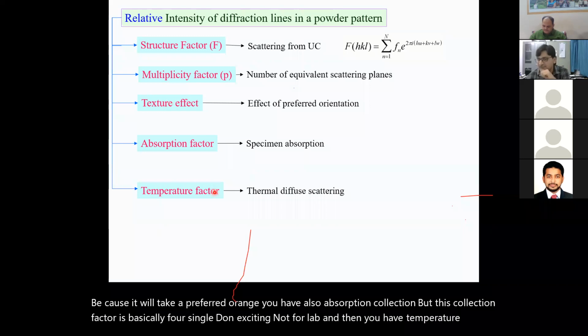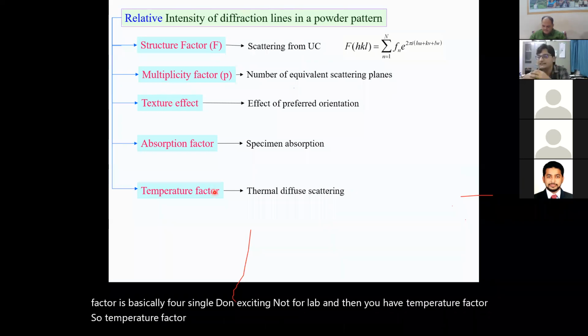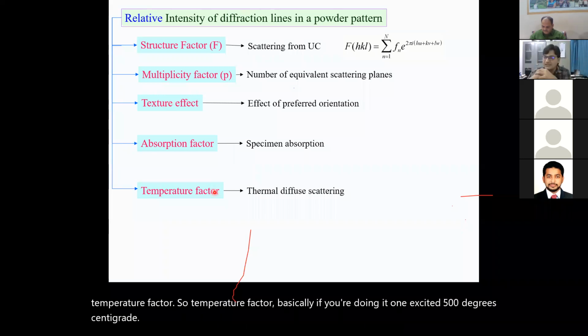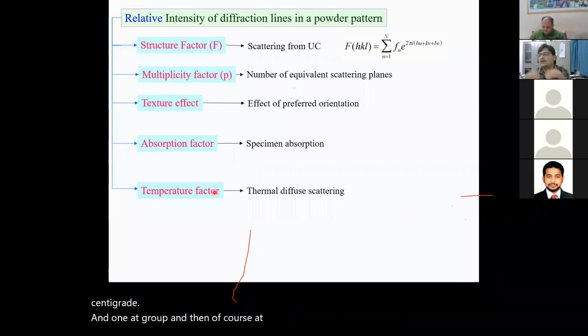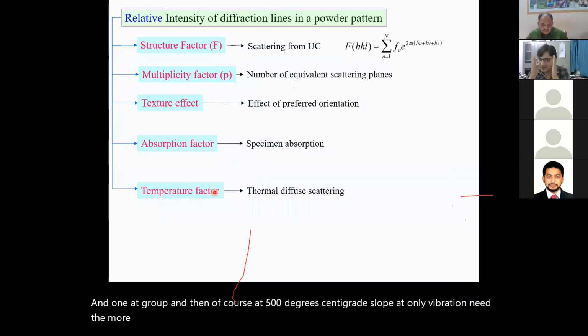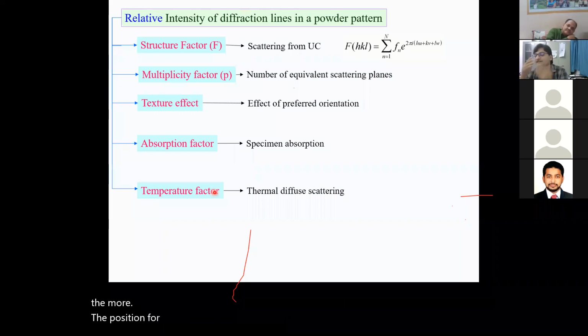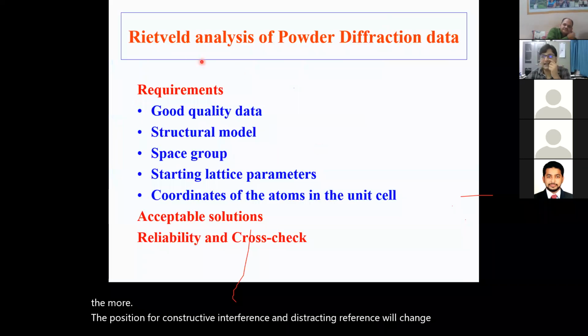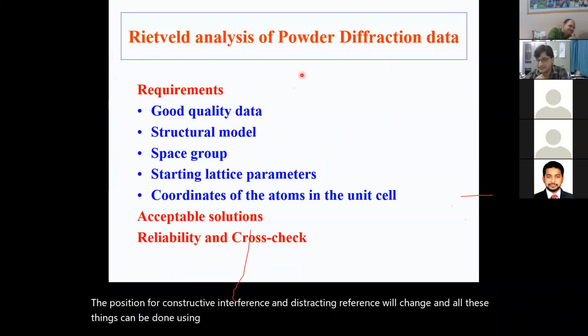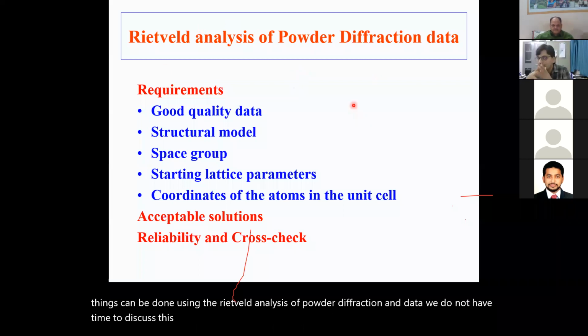For the temperature factor, if you are doing one XRD at 500 degrees centigrade and one at room temperature, then of course at 500 degrees centigrade your atomic vibration will be more. Atomic vibration being more means the positions for constructive and destructive interference will change. So this also you have to take into account, and all these things can be done using Rietveld analysis of powder diffraction data. We do not have time to discuss Rietveld, but you should understand that this is software where you can give some initial value and then refine, like any refinement program.